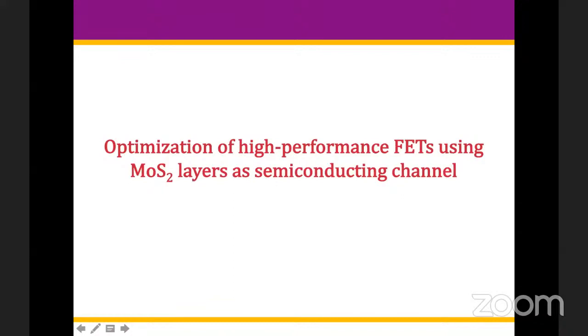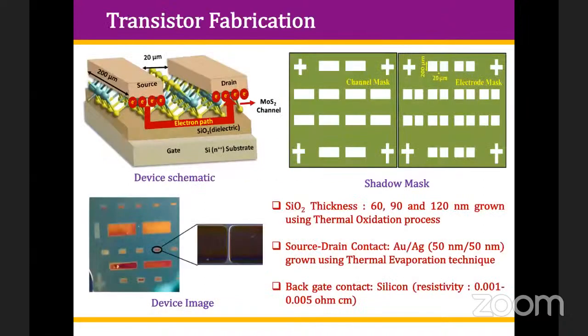So I will go to another application, the transistor which we try to make with the MoS2, because the ultimate goal is that we should go with transistors with smaller nodes. If with a monolayer we can make the FET, then the scalability issue can be resolved, and we can go beyond Moore's law more and more. In this case, we use silicon as the gate, which is a degenerate semiconductor having very good conductivity. You can see here, resistivity is very, very low. And then silicon dioxide as the dielectric layer. And on top of that, we put the MoS2 as the channel.